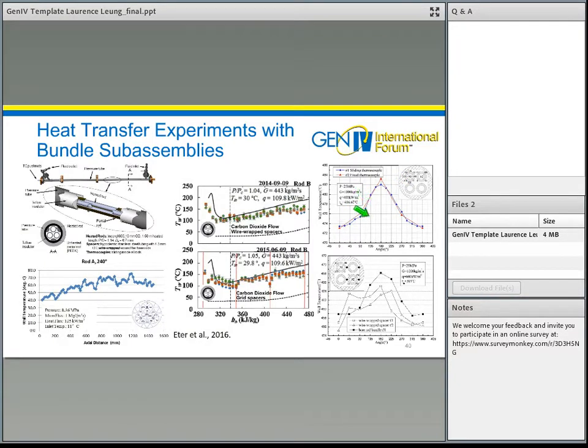This is a comparison of the circumferential heat transfer, the wall temperature measurement that we have. This is the movable thermocouple in very small angle increments, and those are the fixed thermocouples. You can see that both agree very well between the movable and the fixed thermocouples, and that shows the rod performance is very good.